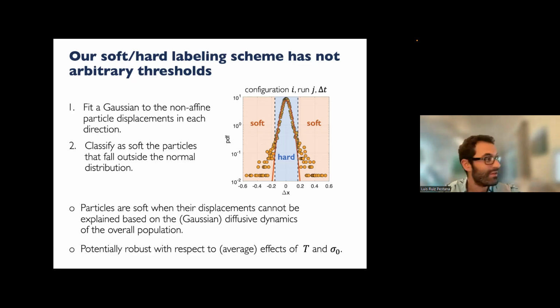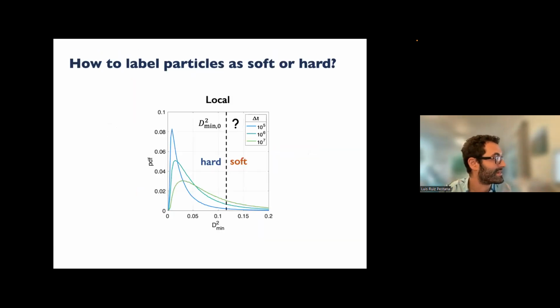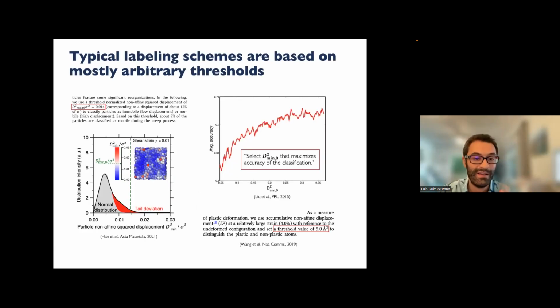Other materials, if you think about, let me go back to this slide here. If you think about choosing a fixed threshold to quantify soft or hard particles, you see that the curves of displacement move over time. So that threshold will change over time as well. So we need something dynamic that actually can identify soft particles as the system evolves.